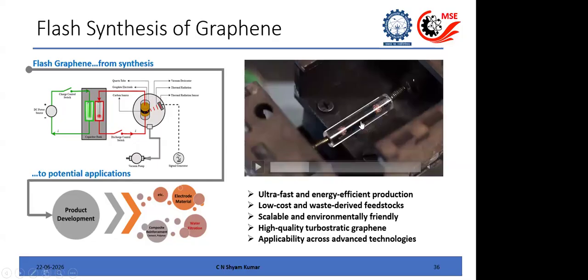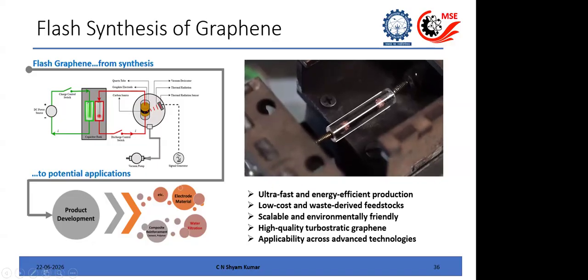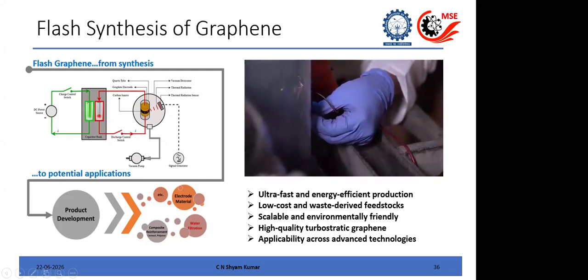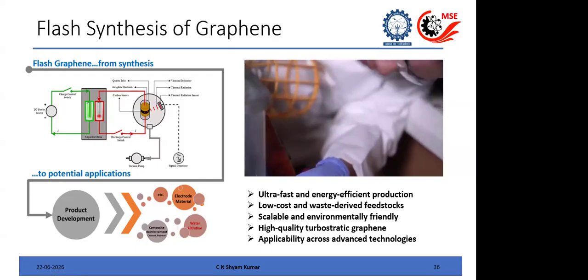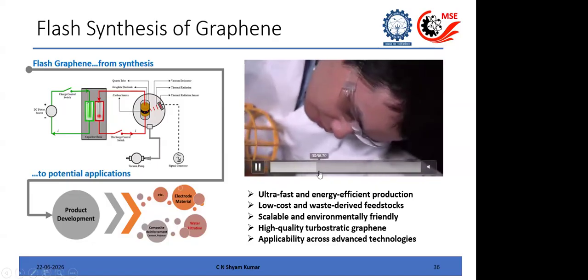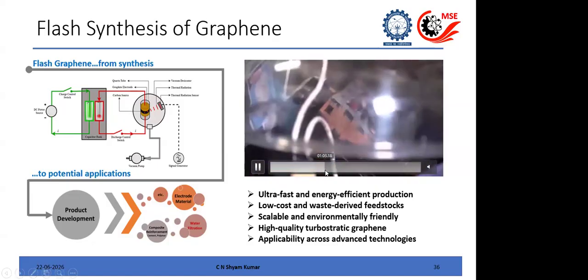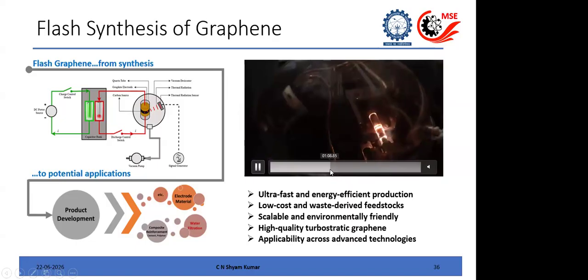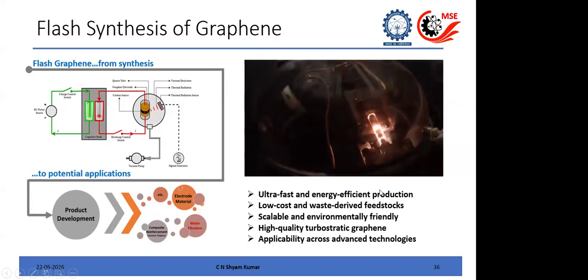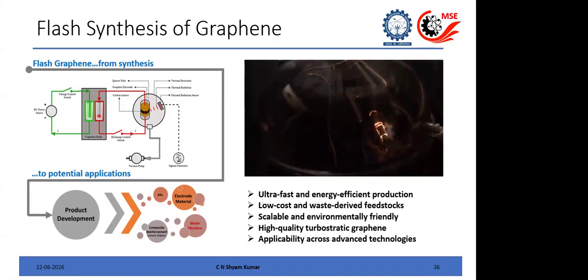You can't flash biomass as such, because there should be some kind of conductivity associated with it. So either you mix it with some conductive carbon, or you initially carbonize it to some extent and then do this, and then you can give very high current and voltage. And you can see that. So this is why it is called flash synthesis.